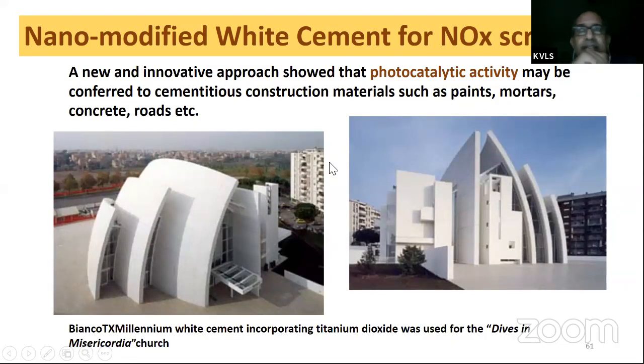Now, titanium dioxide is a photocatalyst. If it is exposed to atmosphere or it is exposed to sunlight, it has the ability to scrub or basically clean the environment of the harmful NOx gases. So what is done is that cement contains these nano titanium dioxide crystals, and when the cement surface is exposed to sunlight, it basically cleans the air which is immediately in contact with the cement surface. So the cement surface becomes self-scrubbing, self-cleaning, and it also has now this